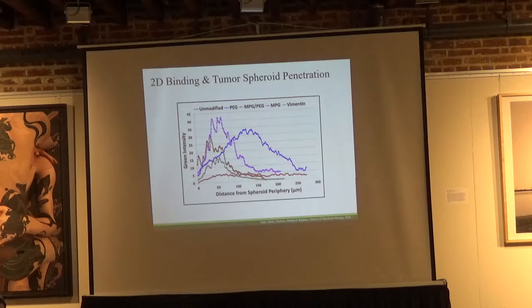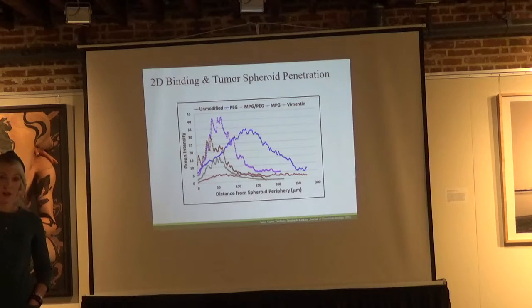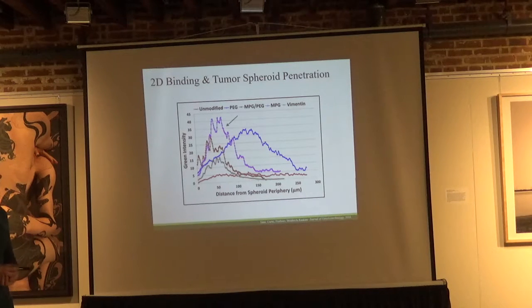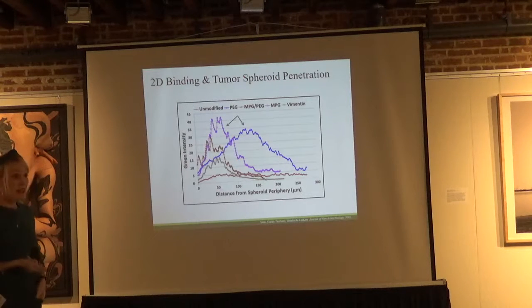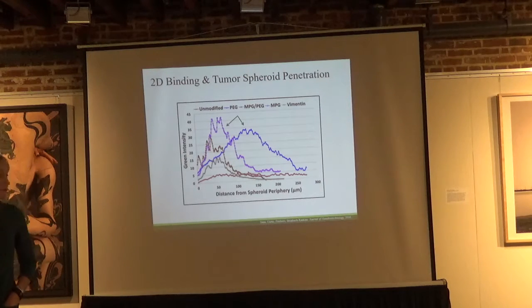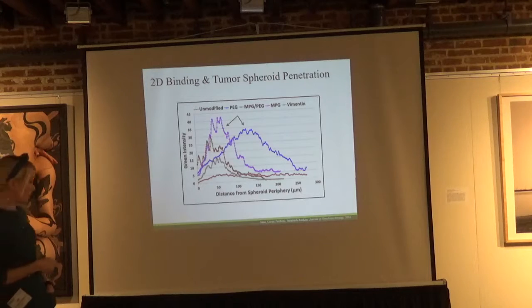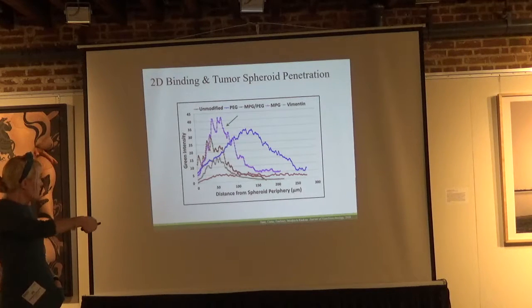And so here we show fluorescent intensity on the y-axis with your distance from the spheroid periphery in microns on the x-axis. So this essentially denotes how far these particles are traversing through these spheroids. And we saw an interesting thing, that if we had MPG modified particles, they did very well in internalizing with cells within about the first 100, 125 microns of the spheroid matrix, whereas the PEG, as expected, would penetrate more deeply. In comparison, you can see from the brown line,